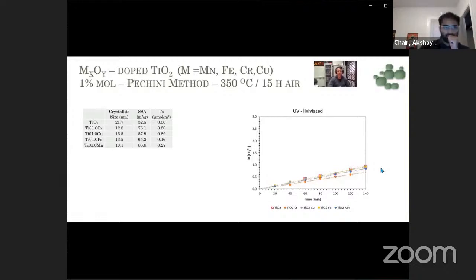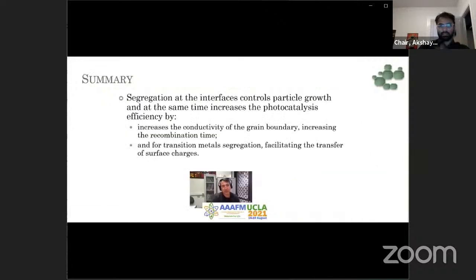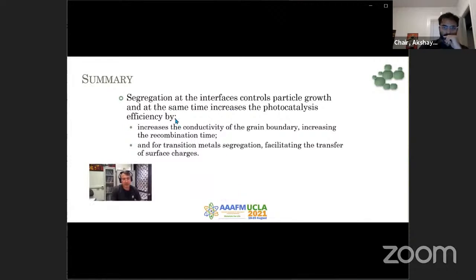This is really a result that gives us the possibility to understand segregation as a very important factor for photocatalysis. In summary, the segregation at interfaces controls the particle growth for nanoparticles and at the same time increases the photocatalysis efficiency by increasing the conductivity of the grain boundary, increasing the recombination time, and for segregation of transition metals, facilitating the transfer of charge, surface charge for the reaction.